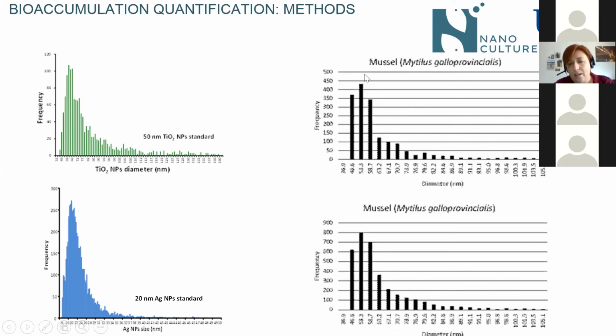And when we expose the mussels to these nanoparticles artificially, what we can see first is that we can recover well the sizes of the nanoparticles that were spiked. This is not a result from the bioaccumulation, but the setup of the technology for the use of the digestion and the recovery of the nanomaterials. We are now working on the analysis of the bioaccumulation studies.